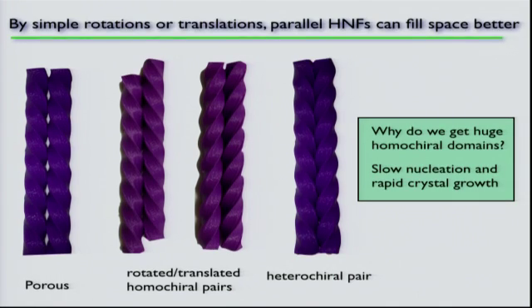So here they are. This is the orientation where the squares are parallel at the top and you have all these holes. But if you just let it slip a quarter of a pitch down, then you can fill the space. If you rotate the two filaments a little bit, you can fill the space. And you can fill the space with a heterochiral pair perfectly well.